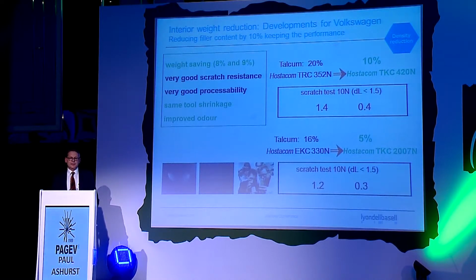Density reduction. This is quite a simple idea, but we've been able to achieve this density reduction of 8%. This is an example of two VW materials. The first example is 20% talc reducing to 10% talc. And the second example is 16% talc reducing to 5% talc. Of course, with the talc reduction comes an improvement in the scratch performance, but also we've been able to achieve this as a drop-in solution. So it fits into the same tool with the same property profile.